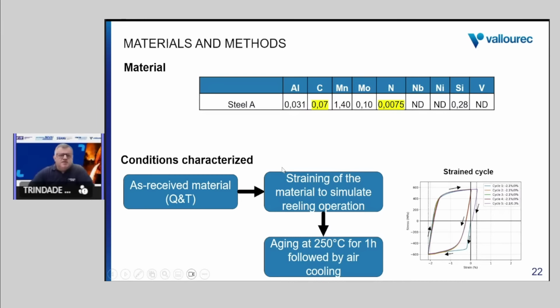So just one example. Let's take this material, a very common material in line pipe. As I told you, it's low carbon, because we need good weldability. Of course, we have nitrogen in those elements, and we have the alloy elements added intentionally. And of course, probably, as Dr. Gramlich showed before, we should have some tramp elements also, but it's not studied here. In this case, Dr. Gramlich, molybdenum is not our tramp element. Molybdenum is our design element. So, just a comment aside.